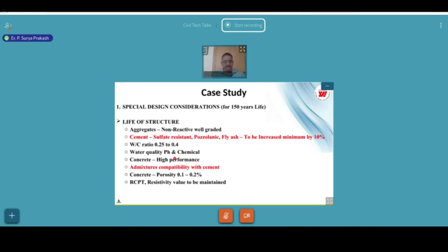the water quality. And the concrete, go for high performance concrete, and I will talk about this in the next slides. And admixtures compatibility with the cement, that is very important. We should test whatever cementitious material that we are using in the concrete, they have to be compatible. Admixtures that we are using, whether it is a plasticizer, retarder, or a flow mix admixture. And the concrete, you have to maintain the porosity between 0.1 to 0.2%. And we have to do the RCPT test and maintain the resistivity value for minimizing the ingress of the contaminants.